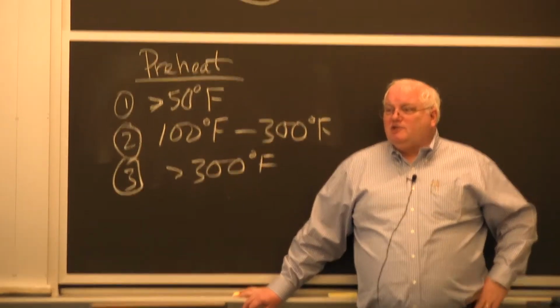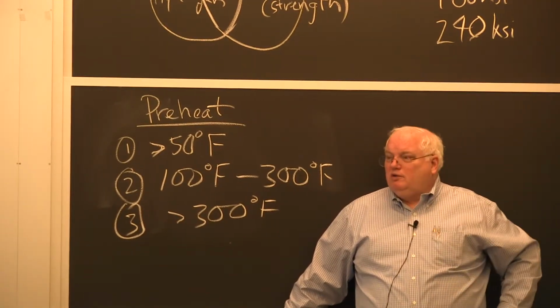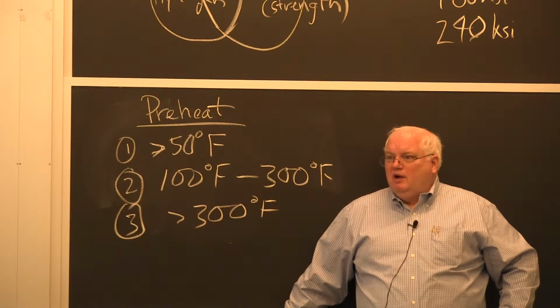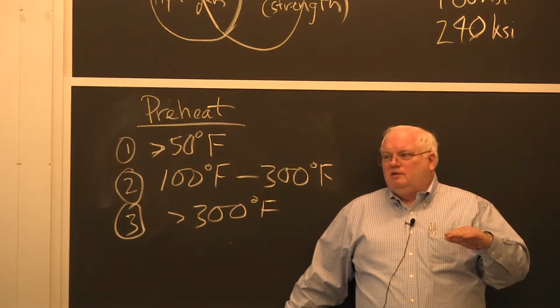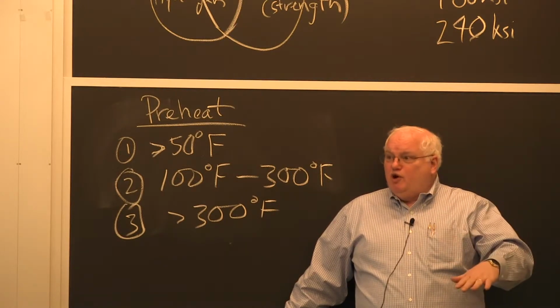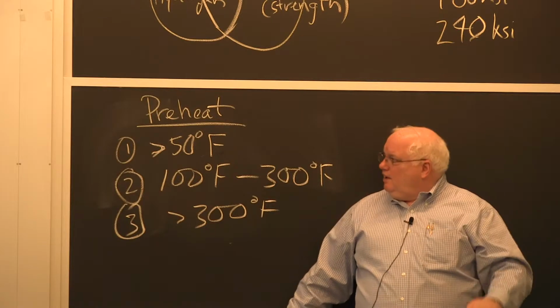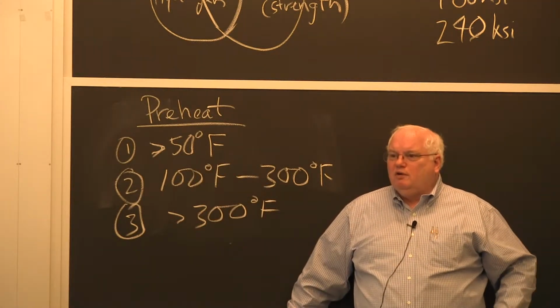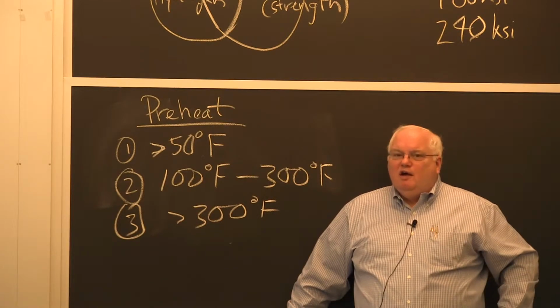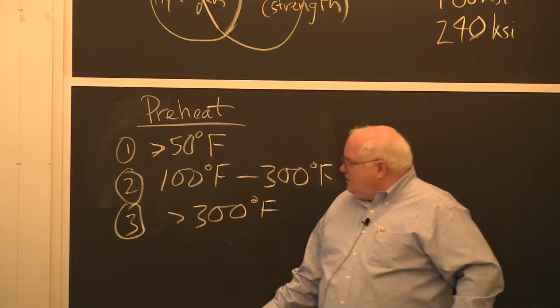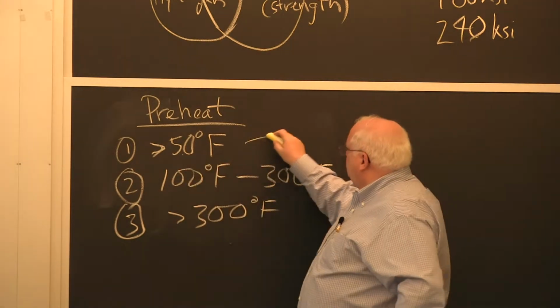Why? They got a minimum temperature. Well, obviously, you don't want to weld on top of ice, right? Why does ASME say 50? Because even though you can't see it, there's a layer of moisture on steel. There's a layer of moisture on that table, as we're talking right now at room temperature. But as you get lower and lower in temperature, towards the freezing point of water, that layer of moisture gets thicker and thicker and thicker. 50 degrees drives off enough moisture that they have found they don't get cracking by welding on steel that's above 50 degrees. So you've got to be at a 50-degree minimum for surface moisture.